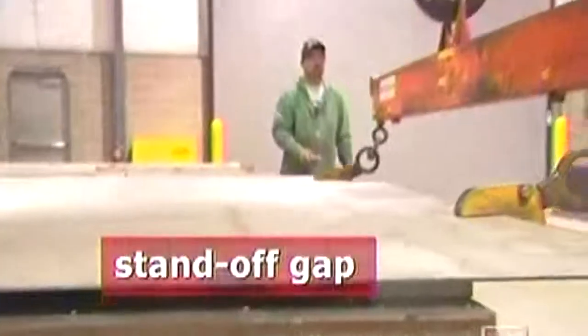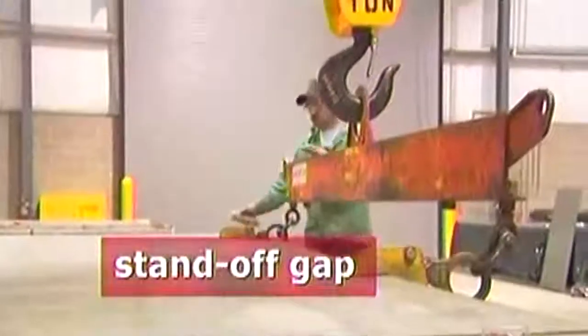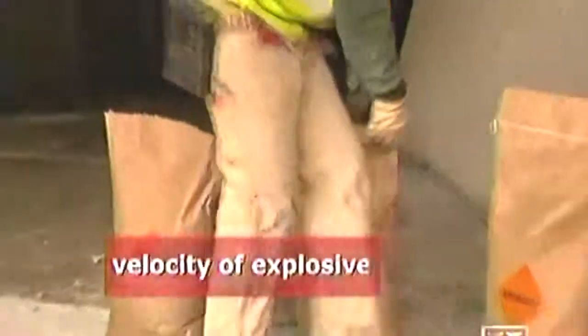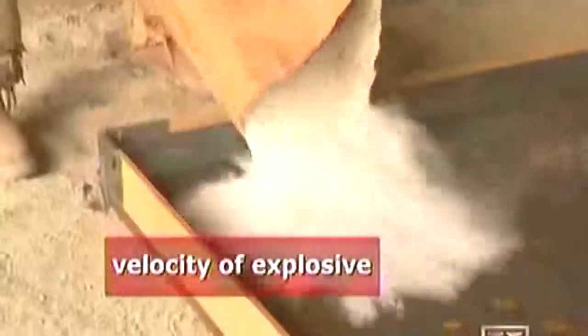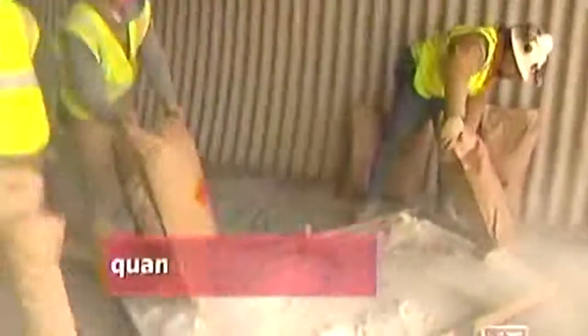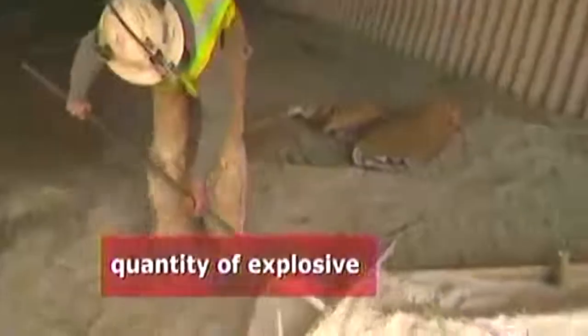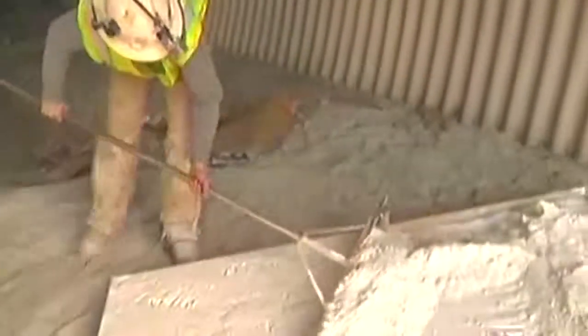The three essential variables of an explosion weld are, first, the standoff gap. The spacing between the two metals needs to be very tightly controlled to ensure the highest quality weld. The second two parameters deal with the explosive. One is the velocity of the explosive, the speed at which it burns, and the height of the bed, or the quantity of explosive which is evenly spread on the top plate.